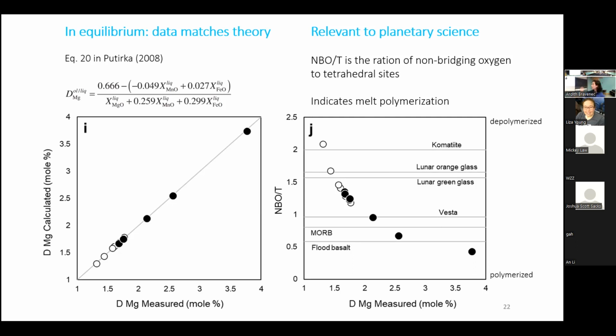But what's interesting to note here is that my values fall within values that are interesting in a planetary science context. They're between MORBs and lunar orange and green glasses. They fall within the range for Vesta. So I've actually synthesized glasses and crystals that appear to be in equilibrium, and the glass isn't anomalous in a planetary science context. So it doesn't seem that it's the composition that's creating that alternate trend line.